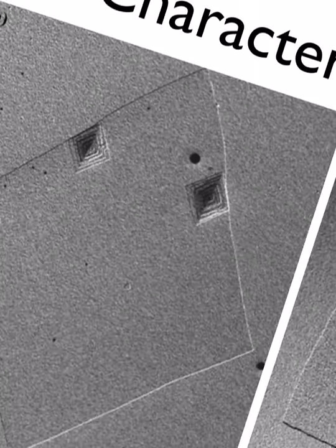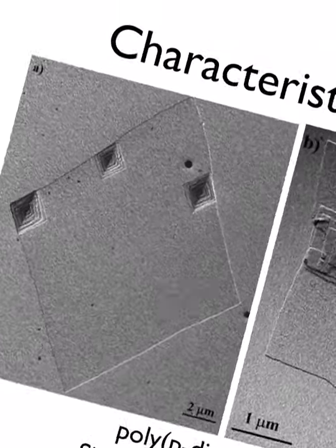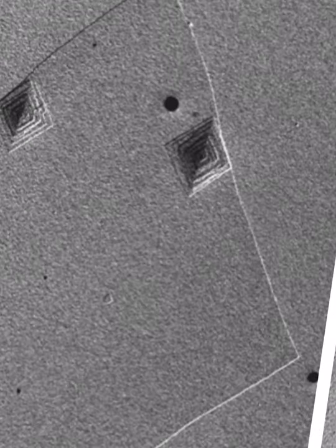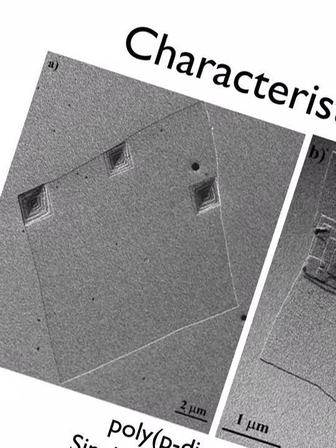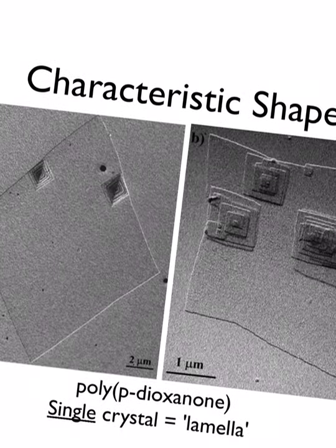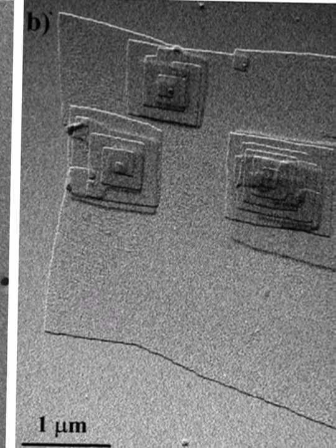Okay, so we get nice behavior in the big crystal shape, and then we have some leftovers, maybe a neighboring chain got involved. It's hard to say exactly, again, what's going on. And so these crystals are forming on top of other crystals, and then nearest this you have more of a squarish looking crystal, and then we have, again, secondary nucleation and growth of other polydioxanone crystals on top of that. And in fact, what you're seeing here, if you look closely, is a screw dislocation forming from those crystals. All right, so we do see this with crystalline matter. Again, don't worry, it's not important. It does happen, but it has no control over mechanical properties, believe me.